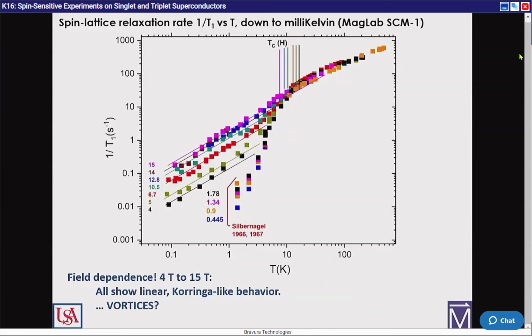So we have the same kind of linear temperature behavior that you would normally associate with the normal state. But we're in the superconducting state. So what's going on here? What makes you think of normal state in the superconducting phase? Vortices. Okay, we've got to think about vortices here. There are two possibilities. Either the vortices are disrupting the natural relaxation of the nuclei themselves, or the superconducting electronic structure itself is being modified by the vortices. We believe it's the latter.